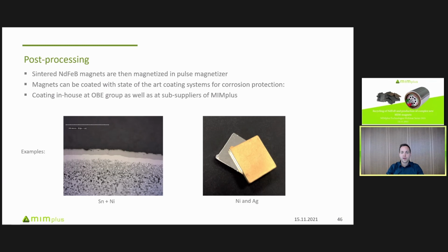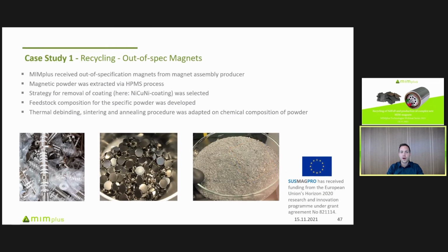Now I'd like to continue with several case studies to show you where the metal injection molding route can be applied. I would start with the recycling process of out-of-specification magnets. We received these magnets from a magnet assembly producer. The magnetic components hadn't been in the range where he wanted to have them. Then we took the magnets, treated them with the HPMS process, chose an appropriate strategy for removal of the coating, which was here nickel-copper-nickel, and we just sieved the nickel-copper-nickel flakes off. Then we developed a feedstock to produce injection molded parts, and then the thermal debinding, sintering and annealing process was adapted to that composition of the powder.